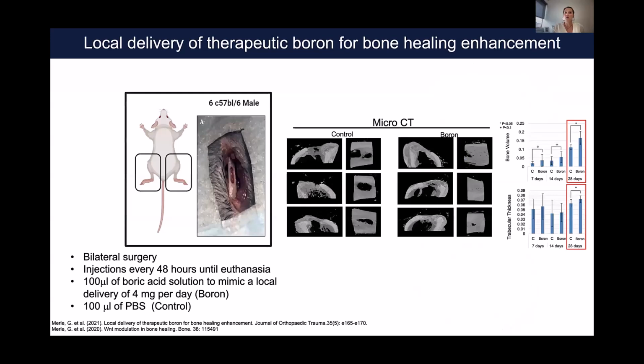And in the meantime, we had a student who was working on boron, showing that boron actually facilitates bone growth. So in that study, we created a bone defect. We created a cortical window defect inside the diaphysis of a mouse. And then we injected boric acid every 2 or 3 days, I don't remember, every 48 hours until euthanasia. And what we saw is that the bone was highly accelerated.